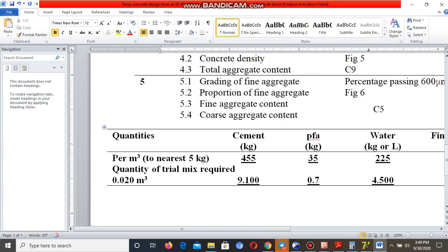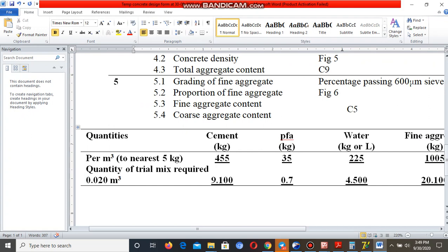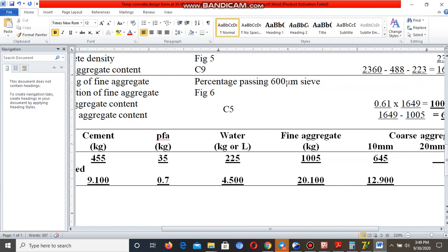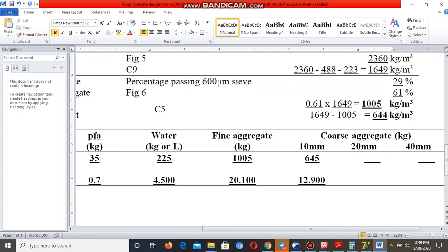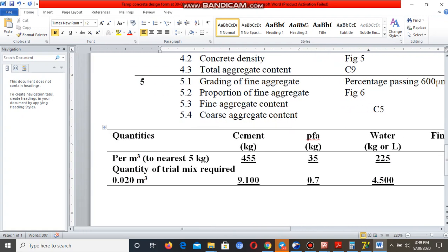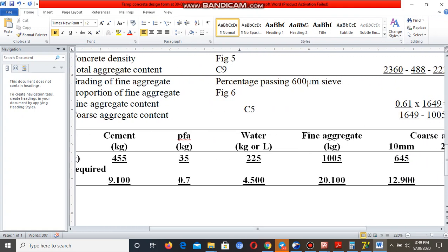You see now the quantities of cement, not for the cube. For one cubic meter, we shall have cement 455 kg. Then we have the pfa, which is around 35 kg.